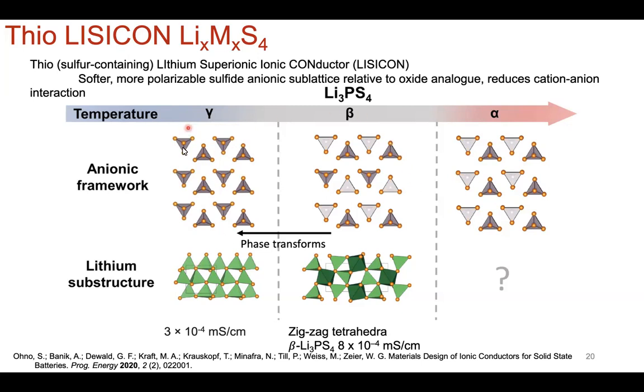And so what you see here is just within the same composition, you have different crystal structures that are temperature dependent. So there's phase transformation with increasing temperature from this gamma phase to this beta phase to potentially whatever this alpha phase is. But already you could see that you can increase the ionic conductivity by more than 2x by just heating up the material a little bit. So then you have to ask yourself, how do I stabilize the high temperature phase at lower temperature? And this is the question that is being asked now. So how do you stabilize a high temperature phase that is thermodynamically higher in energy, but at lower temperatures? What are typical strategies that one would take to do so?